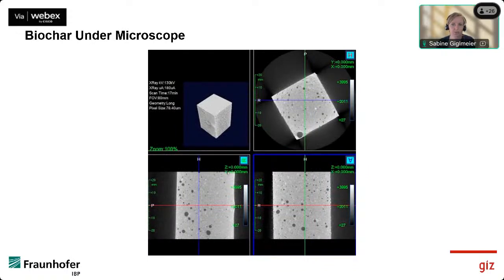These pictures show the material under the microscope, and ideally we see a mortar in which the carbon material has dispersed well in the cement matrix. Of course, this depends on the biochar's particle size. The test specimens now pass through all test procedures which a building material must go through.